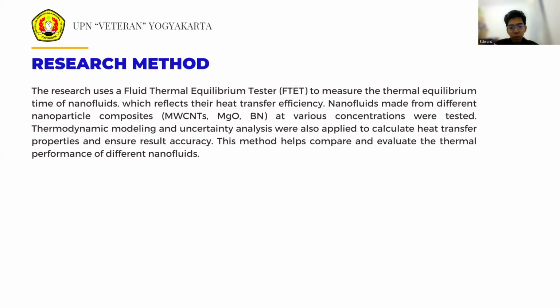In addition to the experimental setup, the study used thermodynamic modeling to analyze the heat transfer characteristics of the nanofluid. Equations were derived to calculate the heat transfer rate, heat transfer coefficient, and specific heat of nanofluids based on their thermal behavior during the test. The thermodynamic model took into account the heat transfer from the boiling water to the nanofluid as well as the specific properties of the fluids involved, including their density, specific heat capacity, and thermal conductivity.